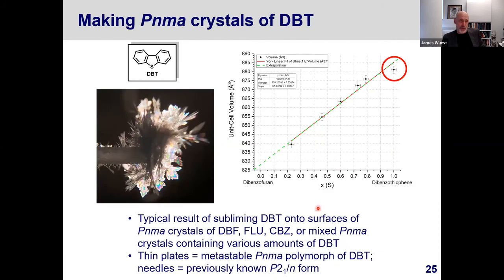So what can you do to solve this problem? Well, what we did is something that's been used occasionally, and it turned out to be surprisingly effective in this case. We developed a system. Basically, you see here a tube, and in that tube we wedged a crystal of the corresponding furan, fluorene, carbazole, or mixed crystals containing thiophene and these other components, and then applied vacuum to this tube that we allowed to draw in vapors by heating the thiophene.